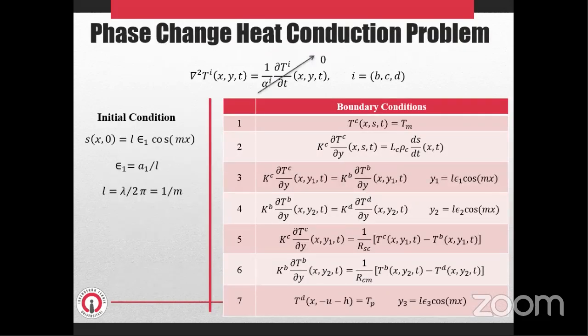Firstly, the two-dimensional heat conduction problem with phase change for solidification of pure metals on a deformable sinusoidal coated mold of finite thickness is considered. The superscripts B, C, D denote solidified shell, coating, and mold, respectively. The solution of the phase change problem is very difficult since the location of the solidification front is not known a priori and must be calculated as a part of the solution.